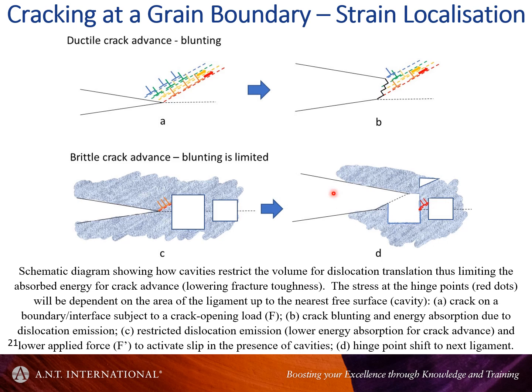So what happens? Well, if you have a bubble-free material and you have a crack, in Mike's simulations, he showed that, basically, the action of slip in a ductile crack is that the crack can grow, but mostly outwards, and it's also blunted, so you don't get this stress intensity here. You get an actual blunting of the crack, and that will tend to diminish any further advancement of the crack because you don't have a sharp edge here. However, in the case of bubbles, if you have a sharp crack and there's a bubble immediately in front of it, the dislocations can't go very far before they intersect the bubble. Eventually they'll slice off the bubble, but then you're creating a hinge arrangement here, and one can speculate that perhaps this sort of thing is happening, and that's why you get that brittle failure when there's a lot of bubbles on the boundary.